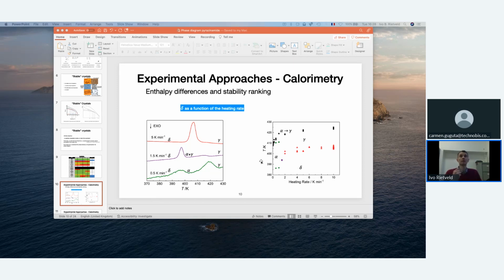Well, if you are interested in thermodynamics, you would like to know where this equilibrium temperature is, but it is impossible to decide by DSC. However, we can have an idea of the enthalpy of transition through the different peaks.